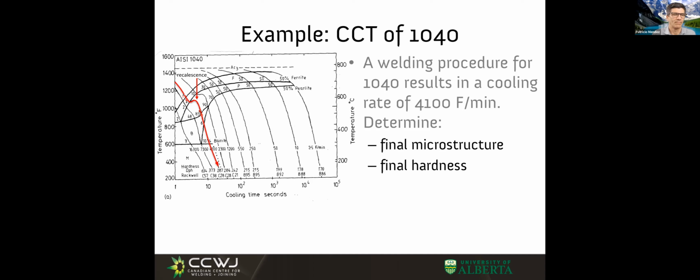What am I getting there? What, as I crossed the line, started to happen? No, pearlite is done. Pearlite is done. Following this diagram, which is not exactly true, but I'm not going to worry about subtleties. Yes, bainite. So we froze 8% of primary ferrite. We froze 85% of pearlite. And now, oh, bainite starts to appear. But if you remember in our previous diagrams, you got either fine pearlite or coarse pearlite or bainite, but you didn't get all of them.